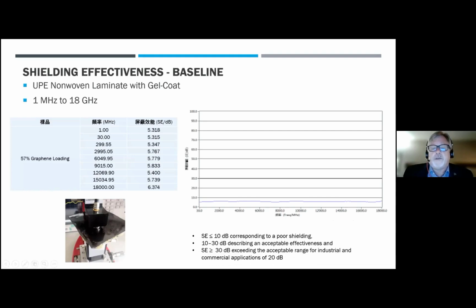So if you look here, you can see that if the decibel range is below 10, you're really getting poor shielding. And you can see in this test, this laminate actually got a lot of graphene in it. And as we're going from 1 megahertz all the way up to 18 gigahertz, which is a pretty high level that we're seeing throughout that whole test run, we're getting well under 10 decibels. So not real good effective shielding in this example here.